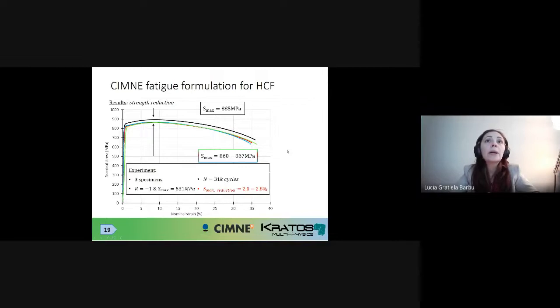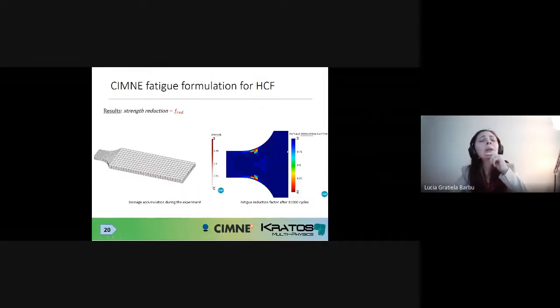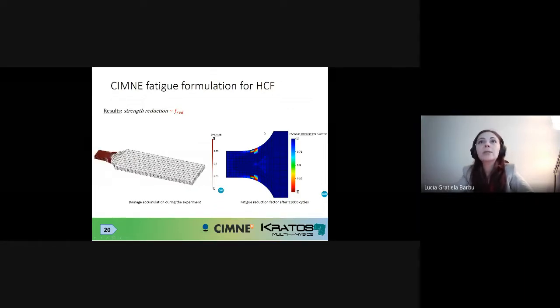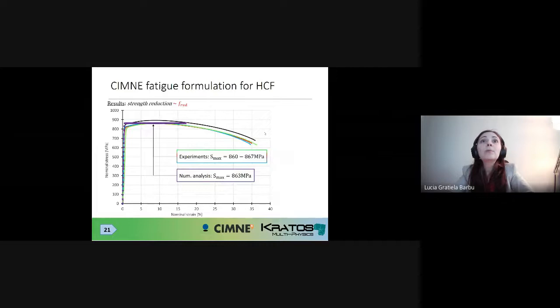Okay, so we started to do the same numerical simulation, where we applied the number of cycles, and then we broke the sample monotonically, and we took a look at what was the reduction factor after 31,000 cycles. You can see here the areas which have reduced strength due to having applied these 31,000 cycles. Then we looked at what was the level of maximum stress that we obtained in the numerical simulation following this exact same load history, let's say.